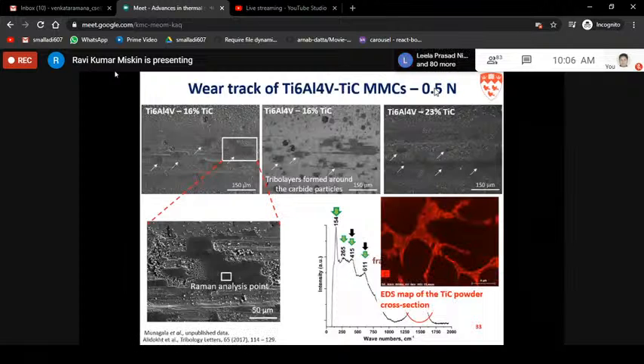Yeah, so that was the free carbon we saw in the initial particle itself. This carbon was coming up onto the wear track, and once it came up, it's a graphitic carbon. Since graphite has a layered structure, it gives lubrication, so it's kind of a solid lubricant, and due to that you are seeing the drop in coefficient of friction. The drop we had seen during the wear test was because you are wearing initially, so you are seeing similar friction. Then once you're wearing out, these carbide particles are getting exposed to your wear track, and there's solid lubrication, formation of layers. That's where your friction and wear are coming down. So that's the science behind why it's coming down.